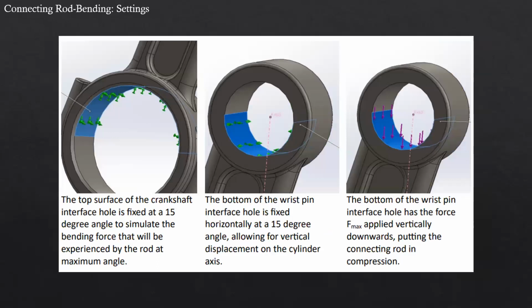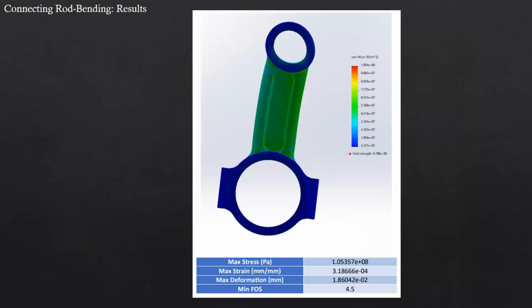Now, for the bending settings, we actually had to set the connecting rod to 15 degrees. That's the maximum angle, and that actually correlates to a downward piston force of 7,655.5 newtons. With those settings, we end up getting a minimum factor of safety of 4.5, which means this rod will not bend within our application.